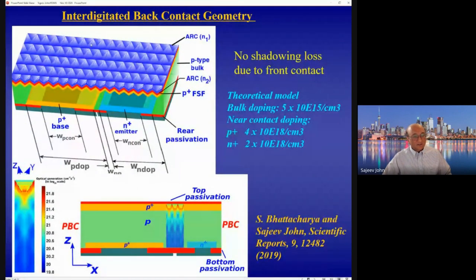It consists of an inverted pyramid structure on the top with a spacing of pyramids on the order of 3.1 microns. We consider a dual layer anti-reflection coating on top and a heavily doped P region on top, which also provides a front surface field to deflect minority carriers. And then we consider this interdigitated back contact geometry with doping regions above these contacts, again, to prevent minority carriers.